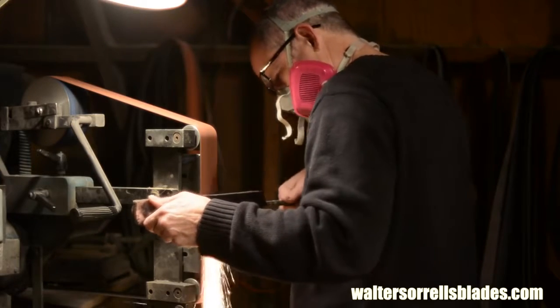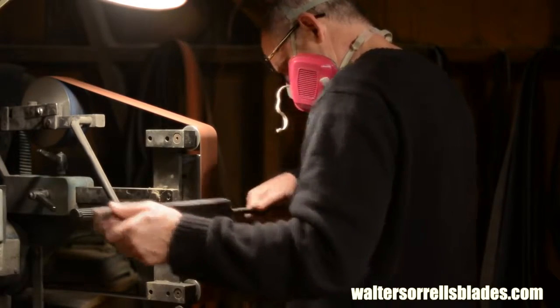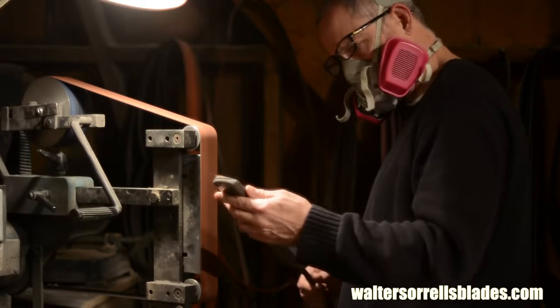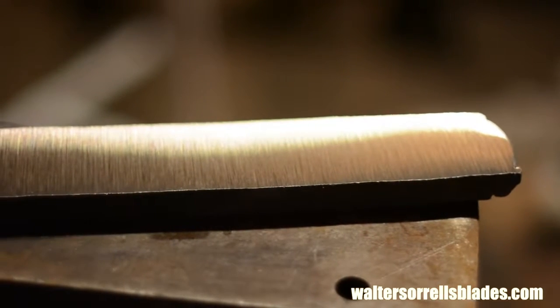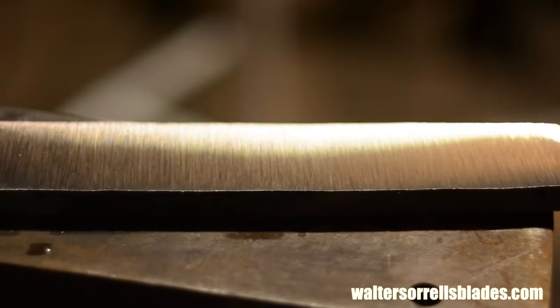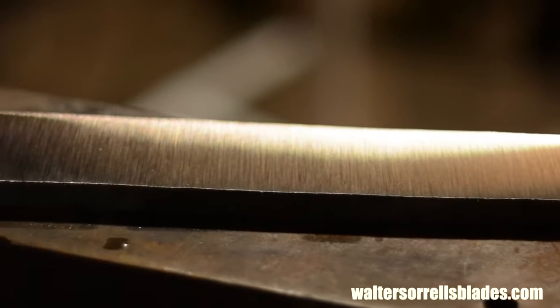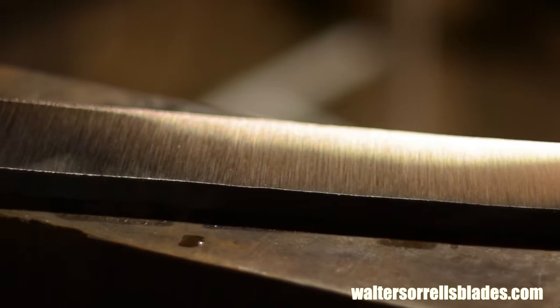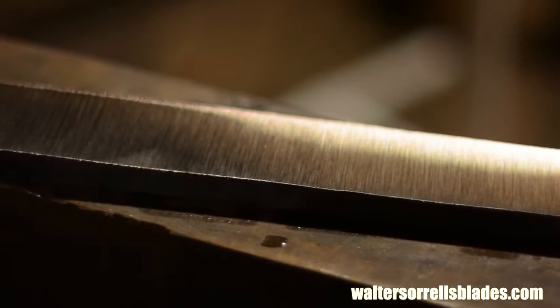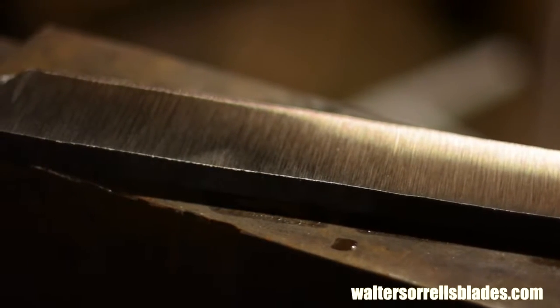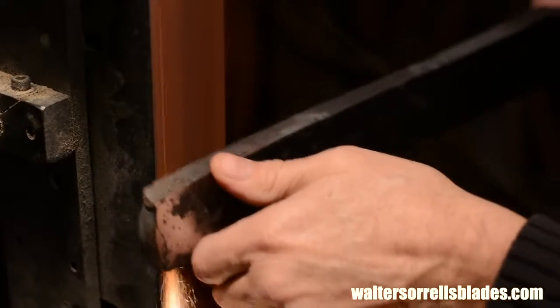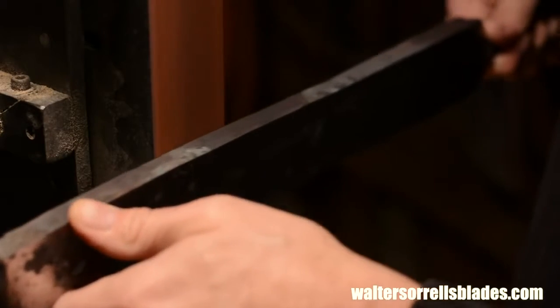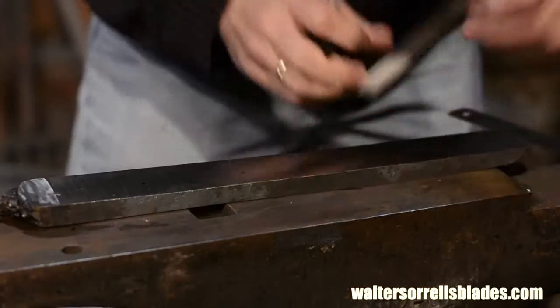Nothing is worse than putting 40 hours into a knife and then finding out as you do the final polish that you've got a bad weld that you can't polish out. Believe me, I know this from hard experience. Every rookie mistake you can make, hey, I've done it. Also, make sure that you grind off any residual weld material from tacking the billet together.